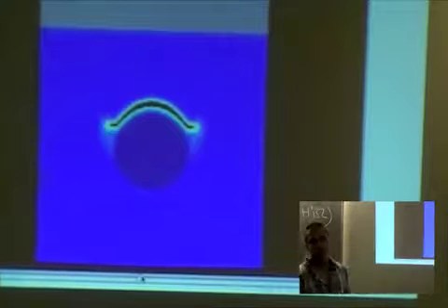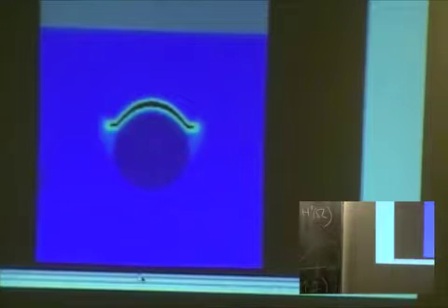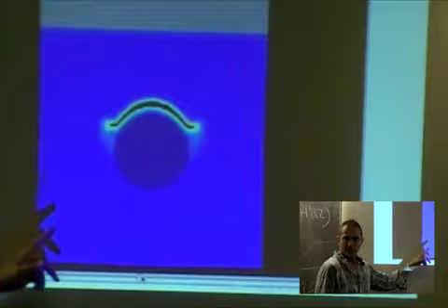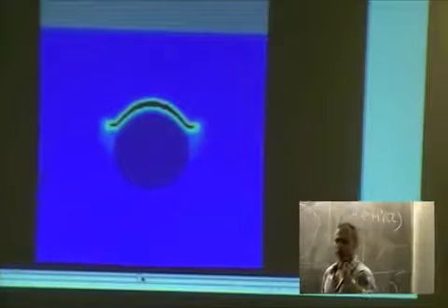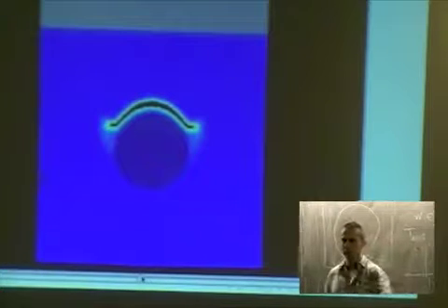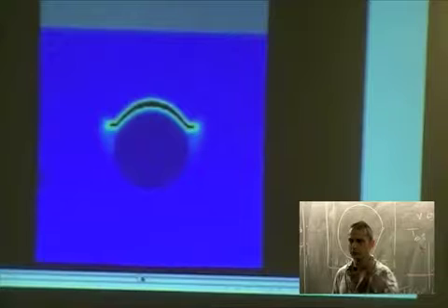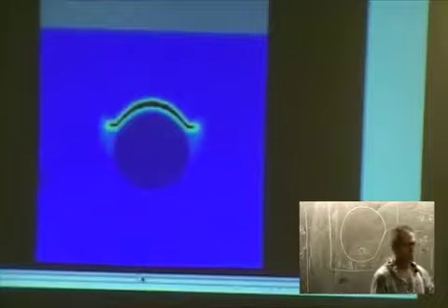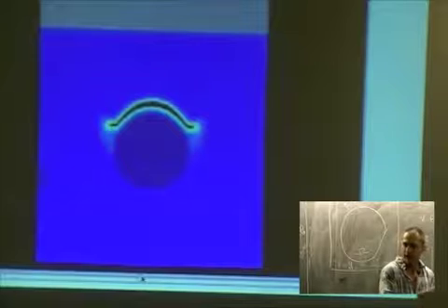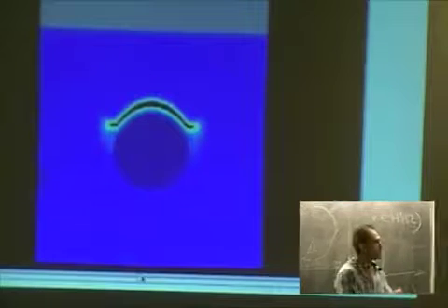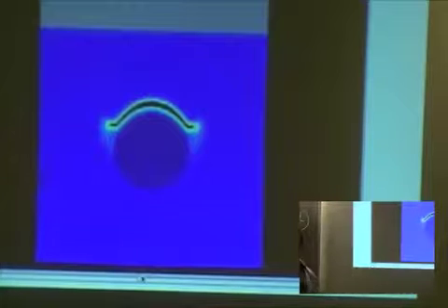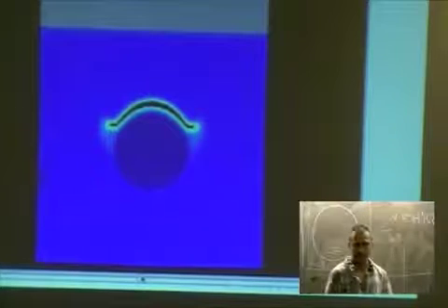Against mesh refinement. Bad idea, mesh refinement. Because mesh refinement drives artificially the crack where maybe it shouldn't go. With mesh refinement, you tend to refine in a place where you already have the crack, and you may miss. You introduce artificial length scales. Yes, exactly. You introduce a length scale.